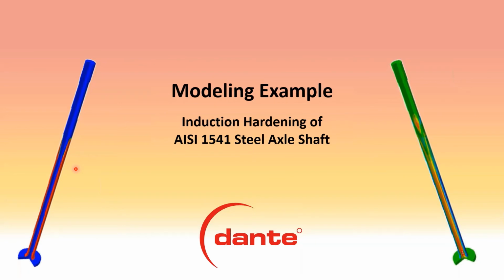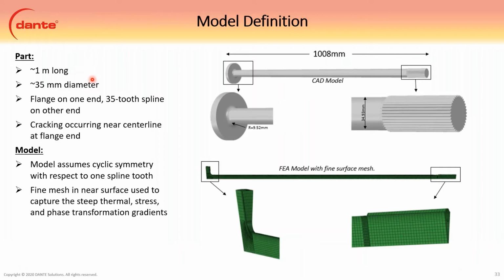All right, this example is induction hardening of a 1541 axle shaft. It's about 1 meter long, 35 millimeter diameter, with a flange on one end and a spline on the other, with cracking occurring in the center line down near the flange. Our model's down here on the bottom, assuming cyclic symmetry, and this meshing is representative of what is needed for a heat treatment simulation mesh. Really fine near the surface to capture the steep thermal stress and phase transformation gradients, and then it can get a little coarser in the core because the gradients decrease.